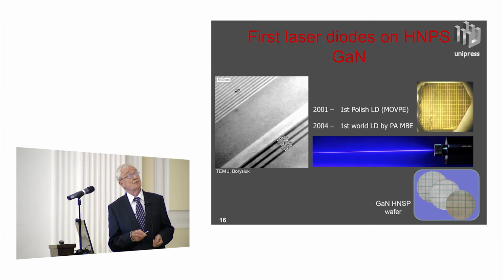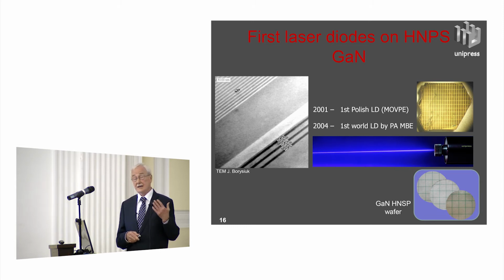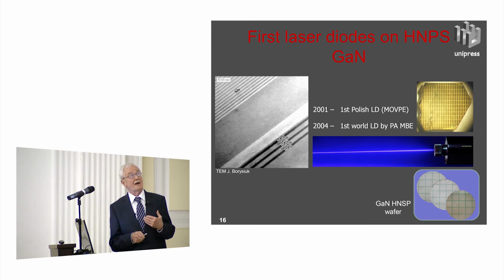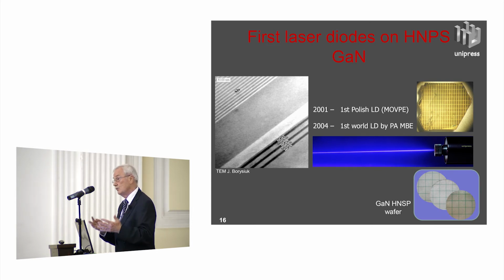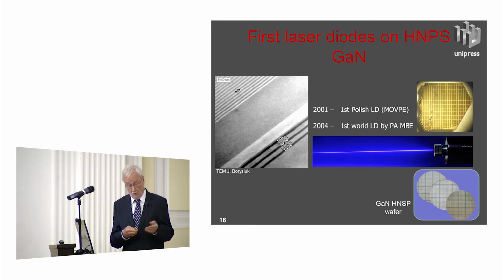The first laser was made in 2001 on such a crystal. And in 2004, we made a laser by another technique, not by MOVPE, which was the standard at this time. We used plasma-assisted MBE, and that's a kind of speciality which we continue up to now. We produce lasers. We can make lasers both with this technology and also with that technology.